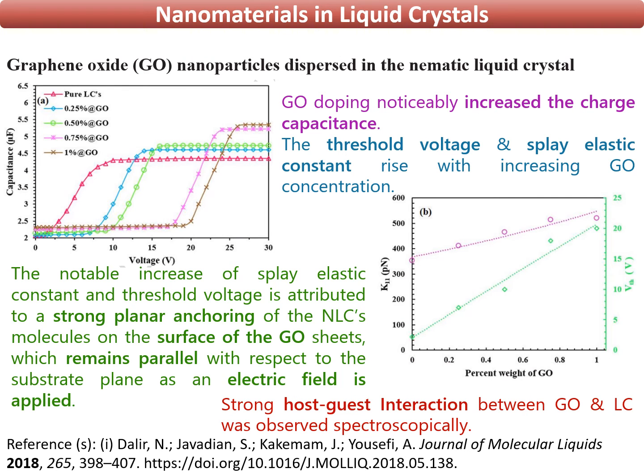In this example, graphene oxide nanoparticles were dispersed in nematic liquid crystals. The capacitance versus voltage graph shows that capacitance was noticeably increased on doping with graphene oxide. Threshold voltage and elastic constants also increased on increasing graphene oxide concentration. This can be attributed to a strong planar anchoring of nematic liquid crystal molecules on the surface of graphene oxide sheets, which remain parallel with respect to the substrate plane as an electric field is applied. So, strong host-guest interaction between graphene oxide and the liquid crystalline phase was proved spectroscopically.